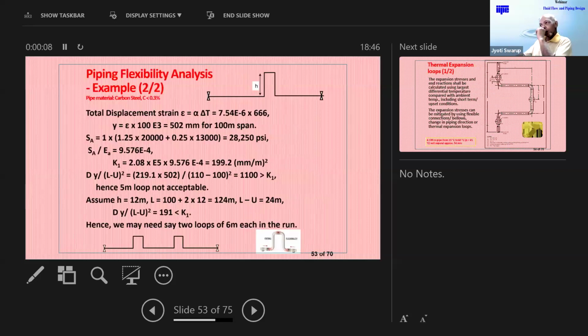So the total displacement strain calculated is about 502 millimeters for a 100-meter span. You can see the pipe will expand by half a meter if there is no expansion loop in the pipe. So you calculate this number. For 5 meters, I found that it is more than K1. Therefore, a 5 meter loop is not acceptable. Now we work backwards and find that a loop of 12 meters is what will be required for satisfying the requirement. And 12 meters is very difficult to physically put.